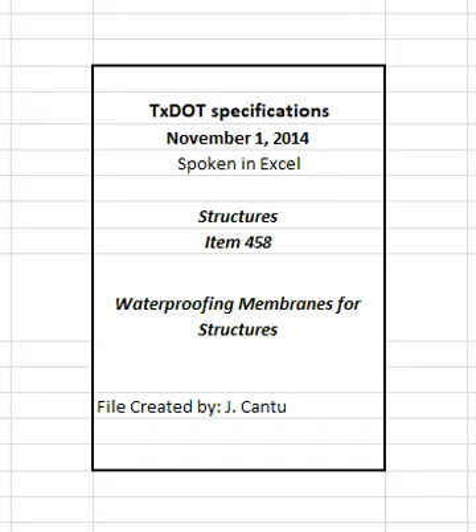Place the protective cover as soon as practicable after placement of the membrane. Clean the membrane surface of dirt and other foreign material before placing the cover material. Apply a coating of cold asphalt emulsion over the membrane at a minimum rate of 4 gallons per 100 square feet of surface. Place the asphalt plank or mat on the coating of cold asphalt emulsion.